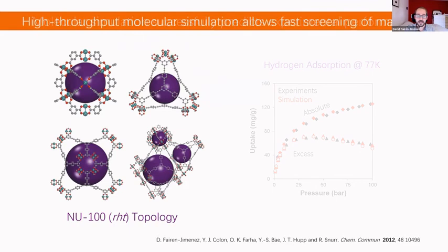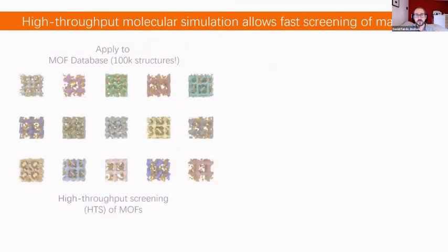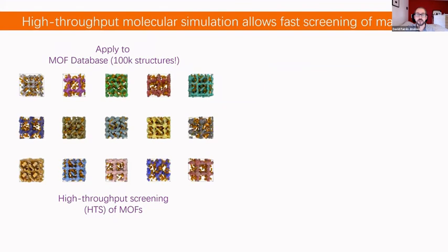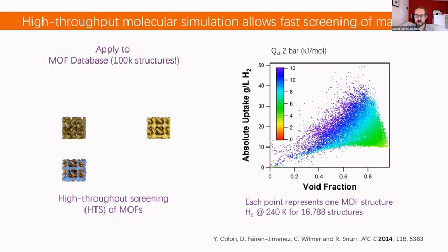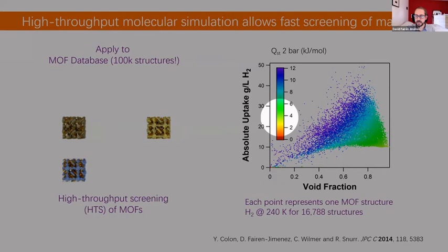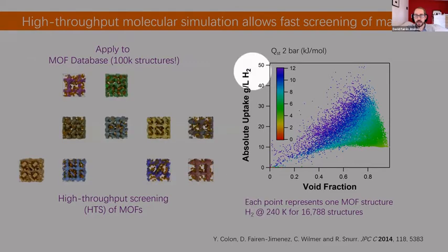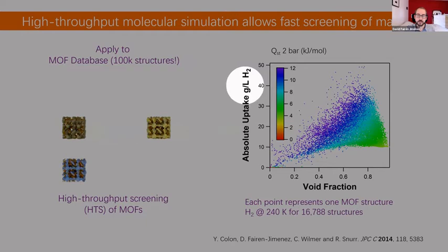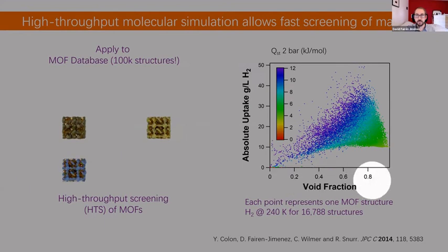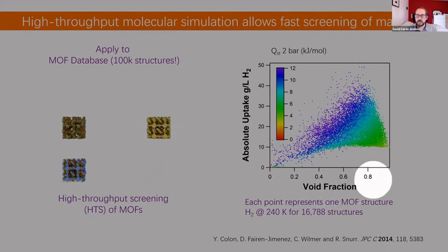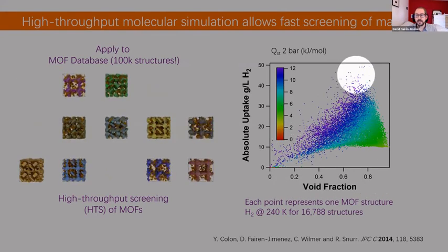If we can do this for one MOF, why not do this for thousands of different structures? And this is basically what is highlighted here. This is again hydrogen storage at 240 K. This is related to the Department of Energy targets. And this is the amount of grams of hydrogen per liter of material that we can really store here. This is represented as a function of the void fraction, basically the porosity, from 0 to 1, of the materials. And we can see 16,000 different points here coming from 16,000 different structures.